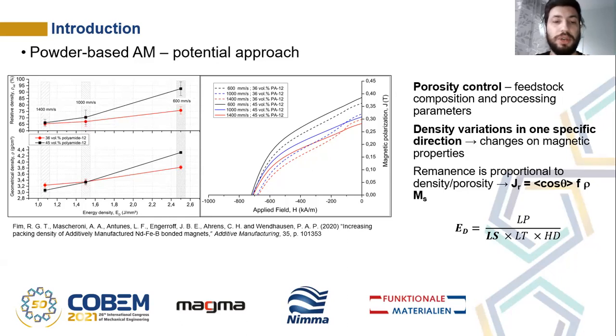This was reported by Fim and co-authors, who presented the influence of processing parameters and feedstock composition on porosity level of neodymium-iron-boron bonded magnets, obtained via powder-based AM. In their work, bonded magnets were obtained varying the fraction of binder in the feedstock and the processing parameters, such as laser scan speed. By the combination of laser scan speed and binder fraction, it was possible to obtain AM-printed magnetic samples with porosity varying between 31 and 5%.